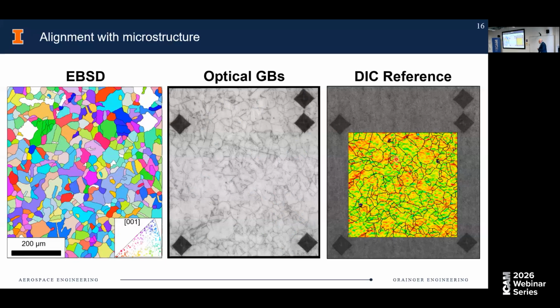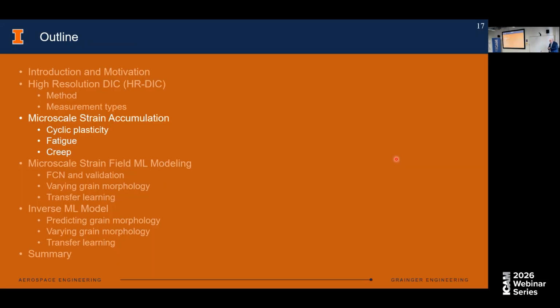We want to correlate these eventually with microstructure, which we will do through correlating with EBSD, and we want to align this with the DIC data set, and that's what these markers are for, to help in the alignment. And we also use in between this optical grain boundary image to help again with the alignment and with any grain boundaries that may be missing from EBSD or from optical. Ultimately, what we have is a combination of strain field at this mesoscale, which would be this sort of collective response of the grains, along with grain boundaries and then grain boundary orientations. Everything on the surface, of course. What I'm going to talk about here, everything has been on the surface. We've done some 3D studies, but I'm not going to talk about that today.